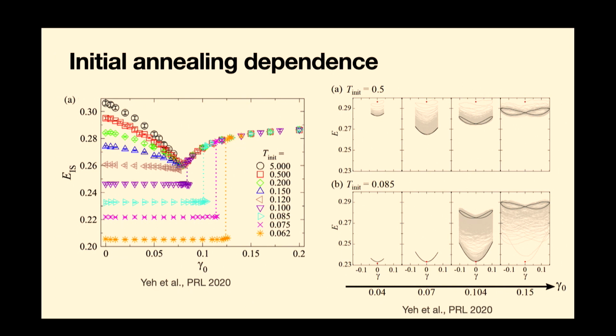Okay, and then beyond that, all the systems lie on the same curve because everything's been fluidized. The energy goes up again as you increase the strain. Right? So here, as you increase strain amplitude, look at steady states. You see first you sort of strain anneal, you improve. You lower the energy further, and then here the energy goes up again as the system becomes more fluidized. Okay? So that's the poorly annealed samples.